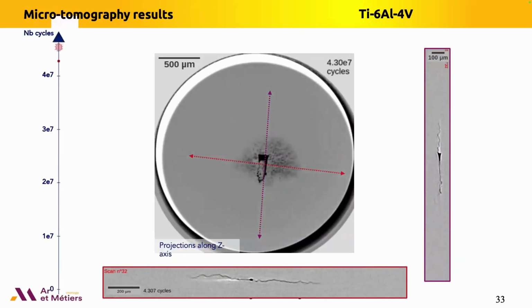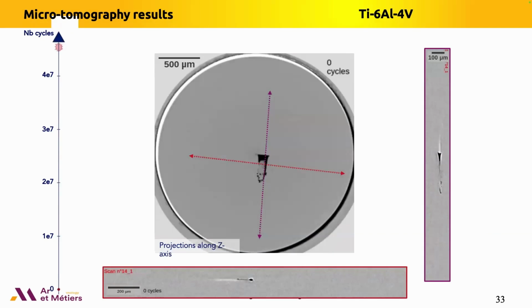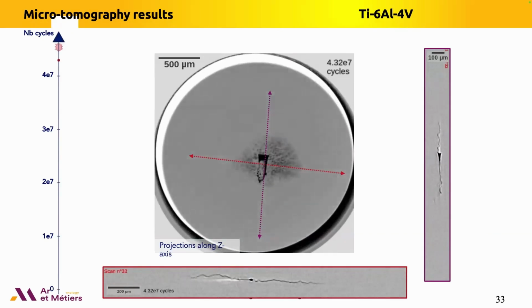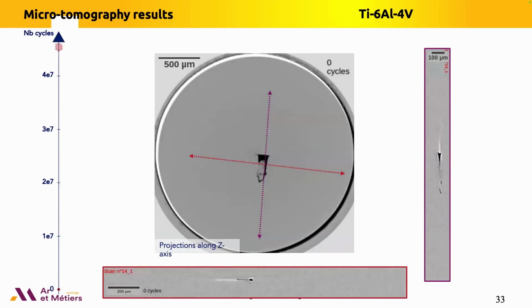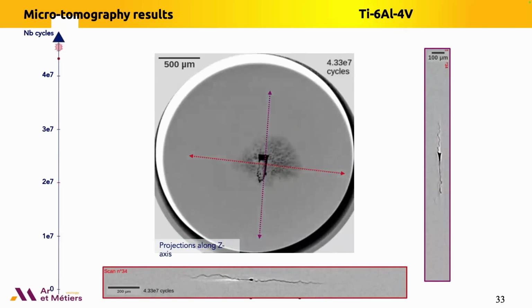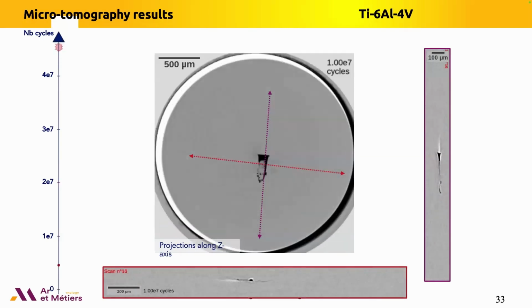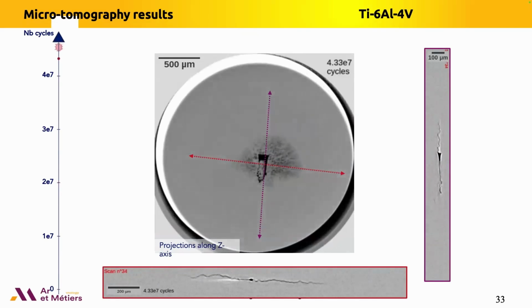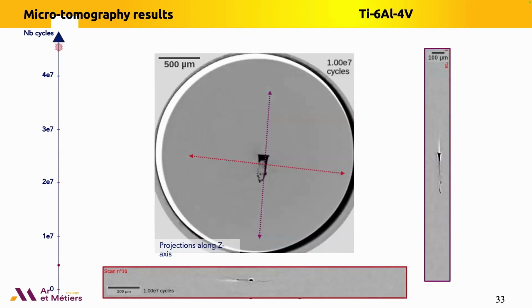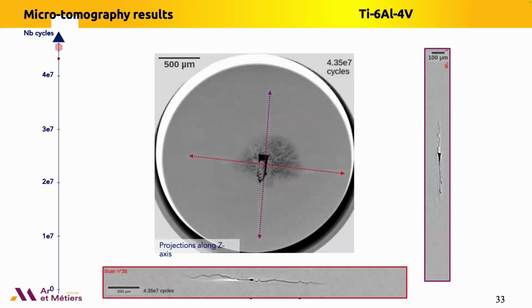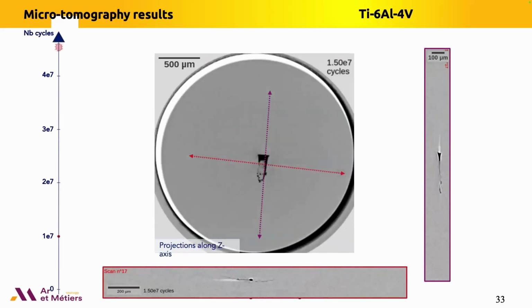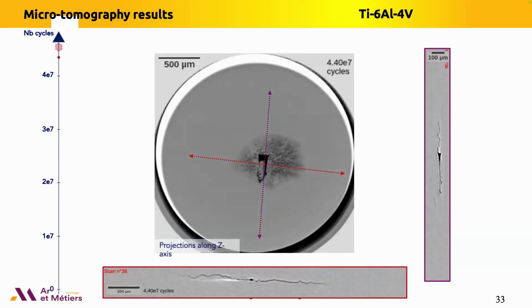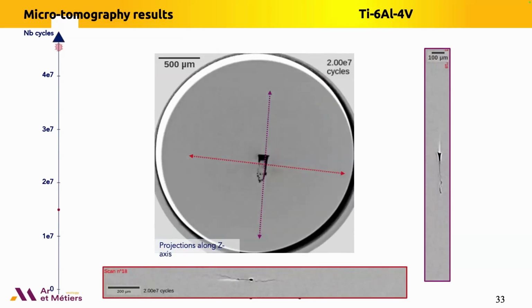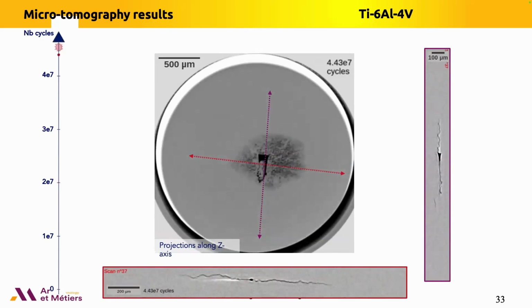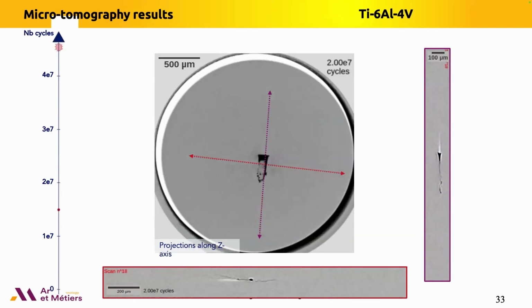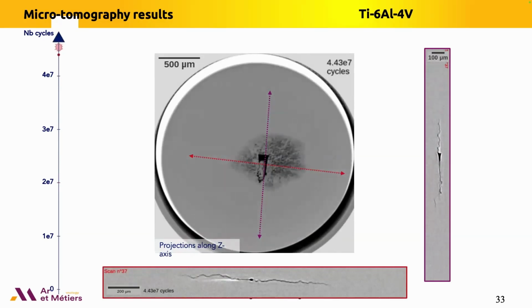So first, I show you here a quick video of the crack initiation and crack propagation obtained by tomography. This is a projection along the vertical axis of the specimen. So you imagine the specimen is loaded perpendicular to the screen, and you can see the projection of the crack. You can see its evolution, and on the right and the bottom, you can see the projection by the 2 cutting planes. So you can see here the artificial defect and then the propagation of the crack. We can reconstruct step by step the propagation of the crack to build its history.